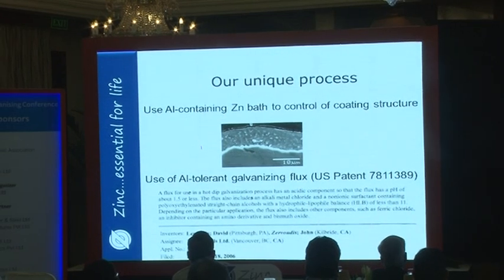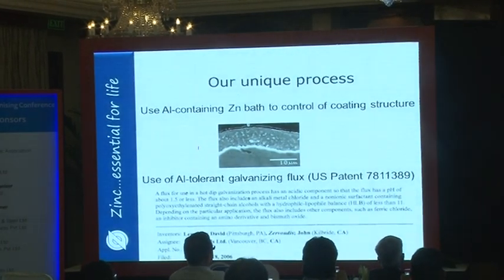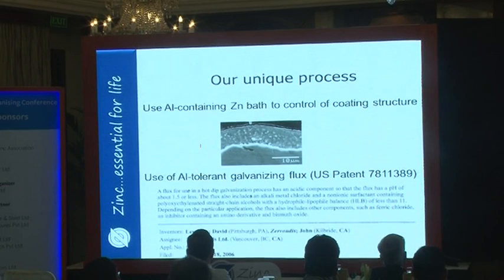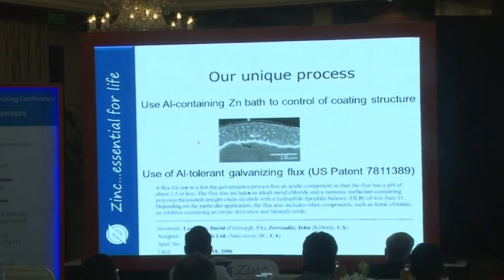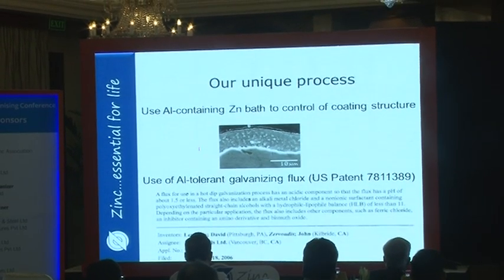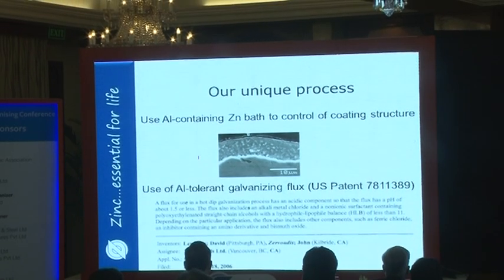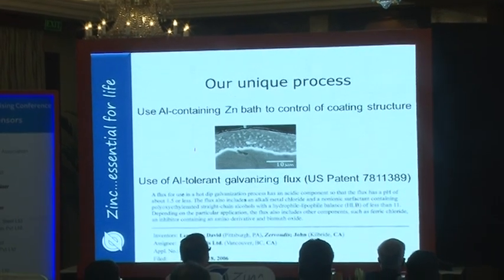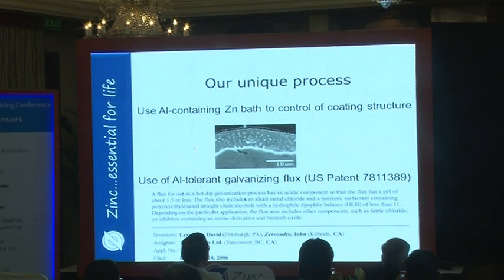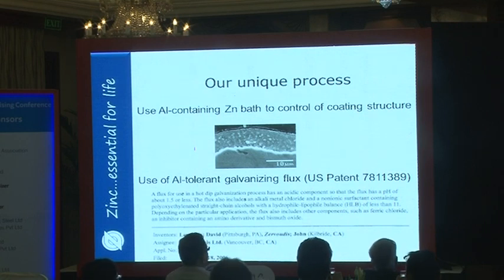This is a very thin layer, and this allows for the ductility of this coating. And also you can see the coating itself is quite thin. Here we show it's about 10 microns, but we can vary this with that air knife that I showed you before. So this is the aluminum tolerant flux patent. It was granted back in 2006, and this was between Ferrotech and Teck Metals, which is shown as the assignee here, and it is allowing this to be used.